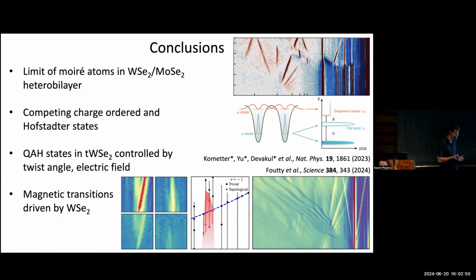That said, there are several examples where people have stacked multiple layers. For example, I talked about magic angle graphene. It turns out that the same type of physics can survive if you stack multiple layers, 3, 4, 5, and people have observed interesting correlation effects and superconductivity in that series of samples. There are other interesting trilayer graphene samples that we've looked at ourselves.